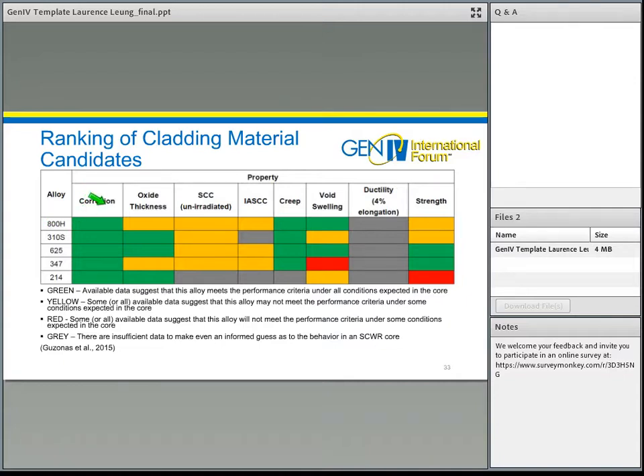For example, corrosion: we see that we have available data that this alloy will meet the corrosion criteria. The orange area means that we have some data available that may or may not meet the performance. The red area means that we have data to show that the alloy will not meet the performance criteria. The gray area is where we don't have sufficient data to quantify the effect on this property for this cladding material.